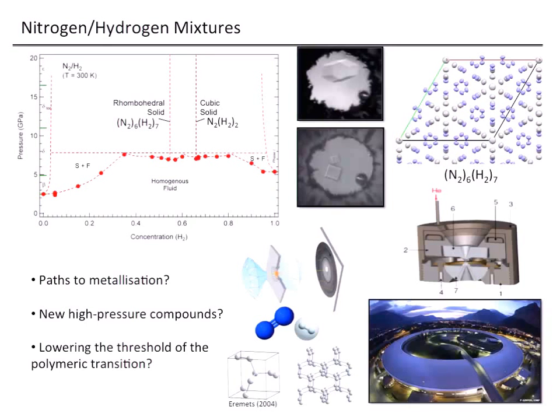So one of my long-term projects when I was there was looking at the binary phase diagram of nitrogen and hydrogen, and measuring specifically the melting curve as a function of composition. So this is hydrogen composition, but also looking for these sorts of van der Waals compounds. And we actually found two in this phase diagram.